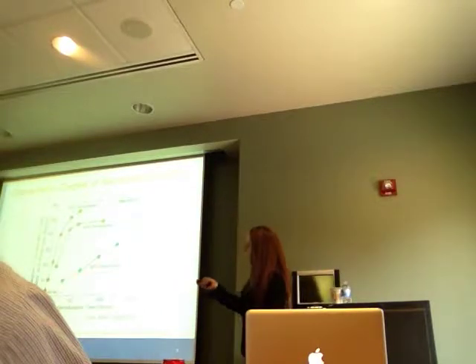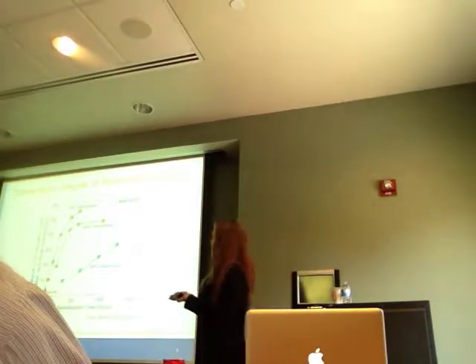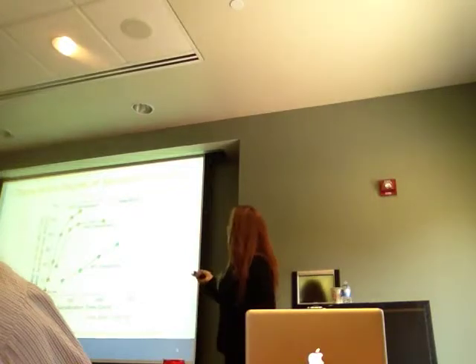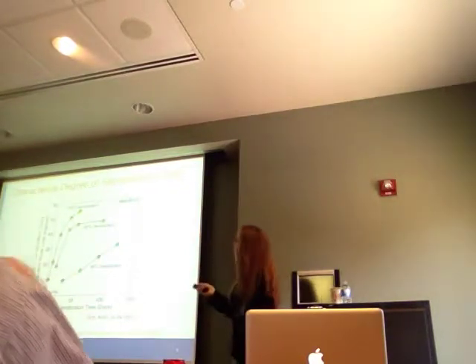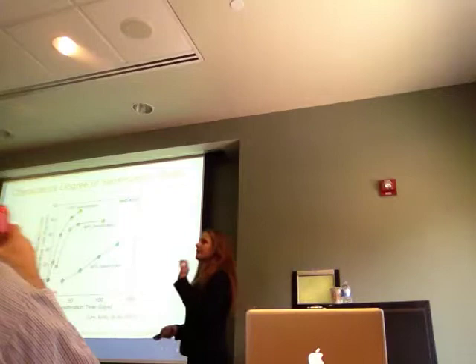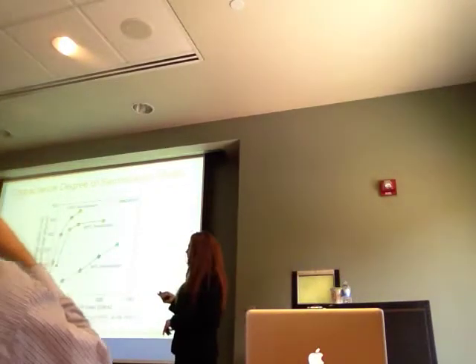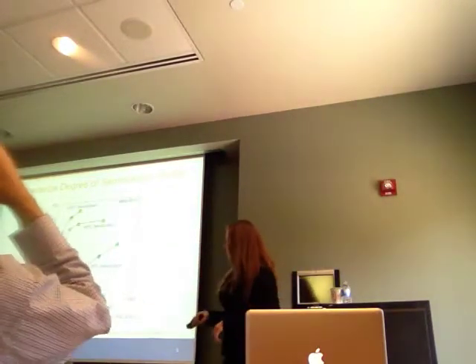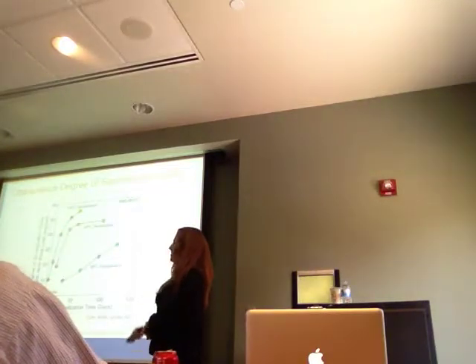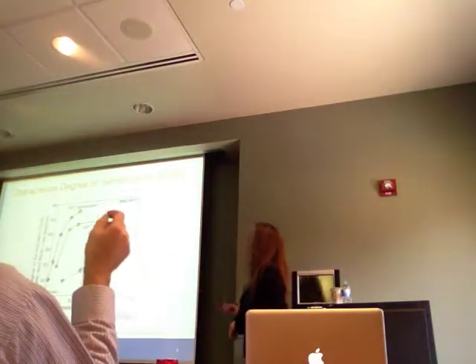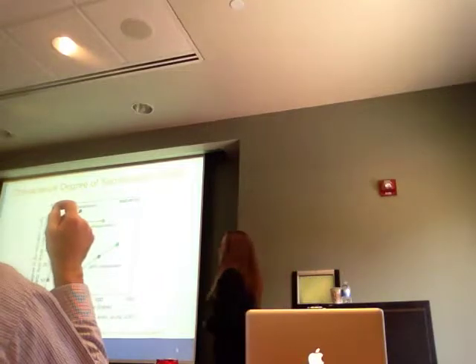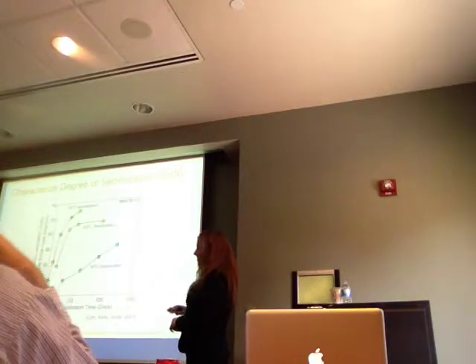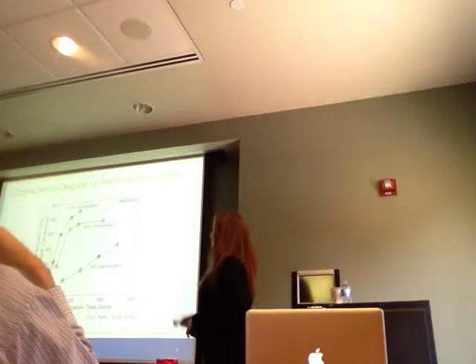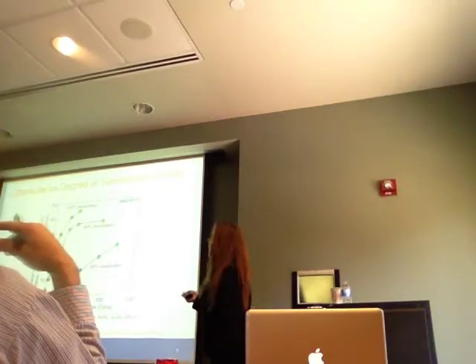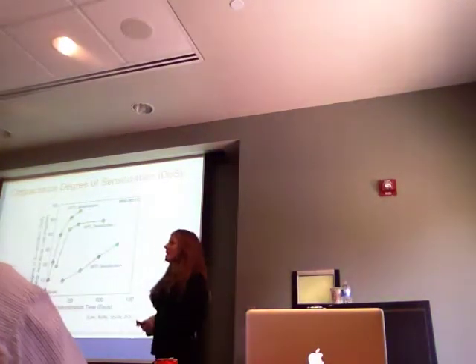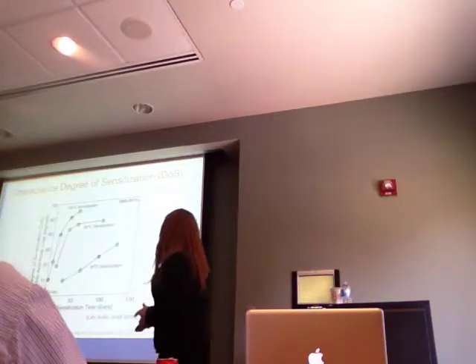So I plotted this mass loss measurement versus our sensitization time at 3 different temperatures. And you can see at very high temperatures, you get very fast sensitization that quickly rises to high DOS measurements. But when you have these low temperature sensitizations, you get a much slower mass loss increase. So these are the 3 temperatures that we'll be looking at, and these are all the conditions that I'll be looking at to characterize intergranular stress corrosion cracking in this work.